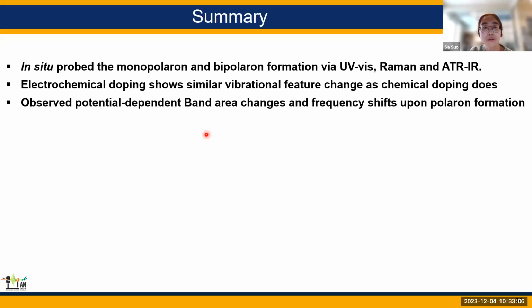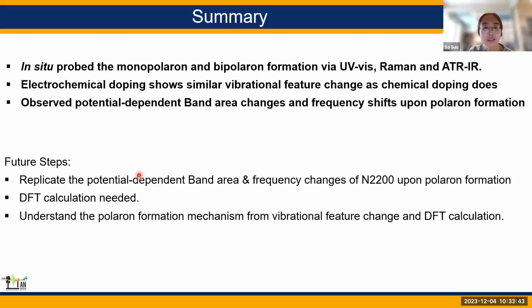So till now, I hope I showed what we did for the in situ probing of the monopolaron and bipolaron formation via these 3 kinds of techniques. I think the major finding is that electrodoping shows similar vibrational feature changes as chemical doping does. And a very interesting phenomenon that we observed, the potential dependent band area changes and also frequency shifts upon polaron formation, needs more simulation and experiment to understand. As a future step, I will replicate the in situ Raman measurement of those vibrational information changes, and also collaborate with the DFT calculation groups to help understand what is happening.